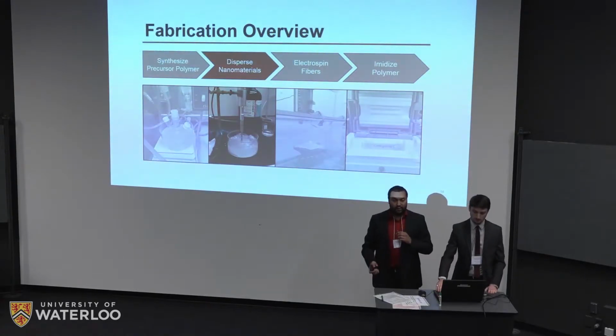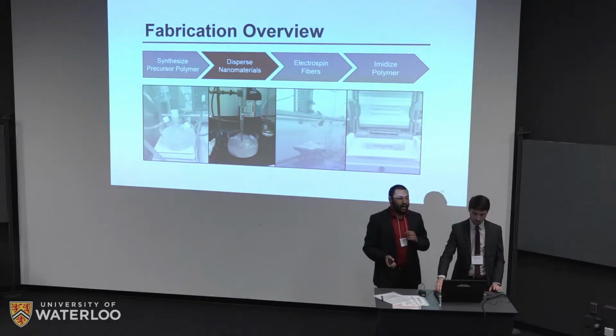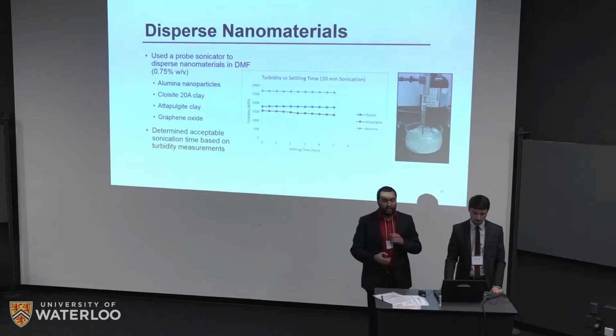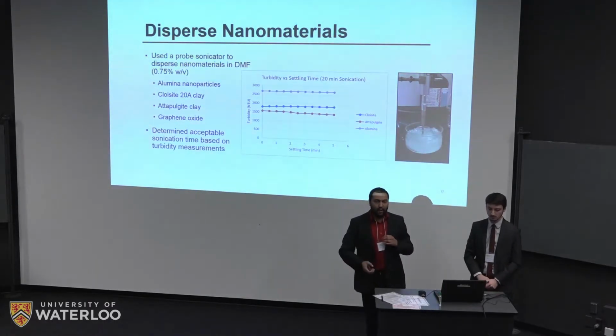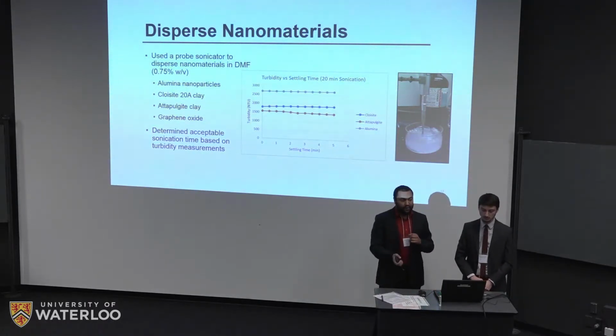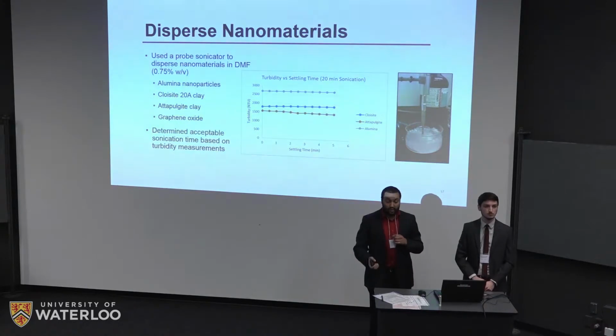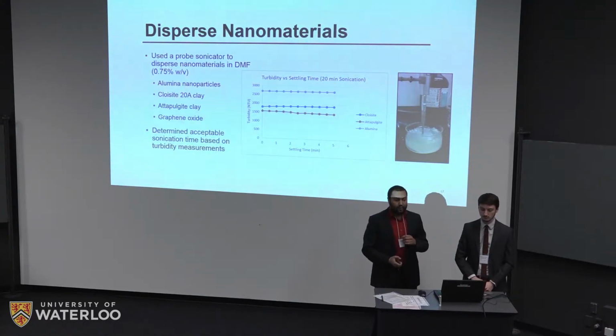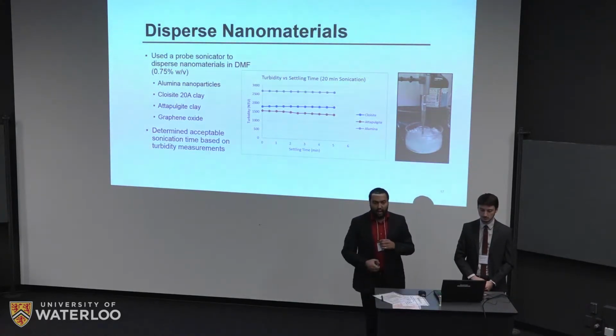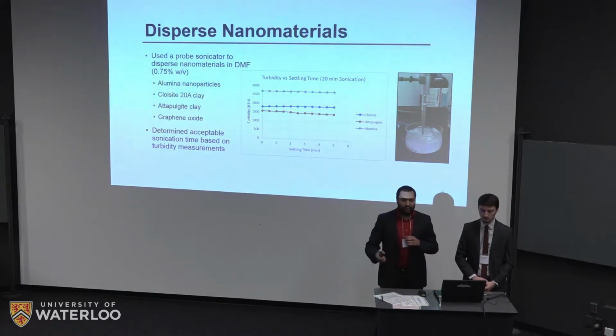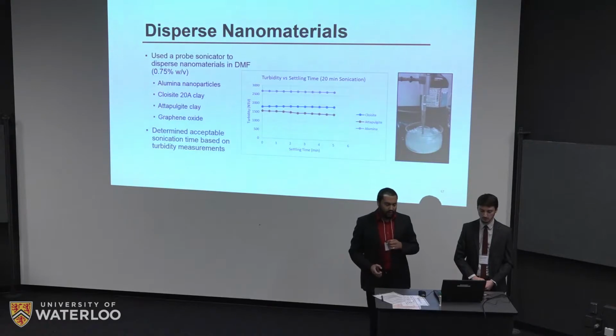Next thing we wanted to do was disperse the nanomaterials. In order to get the properties that we desire, we need to make sure these nanomaterials are well dispersed within the polymer matrix. And so for this reason, we did some dispersion studies. We used a turbidimeter to measure the settling rates of different nanomaterials dispersed in DMF, which is the solvent that we're using.